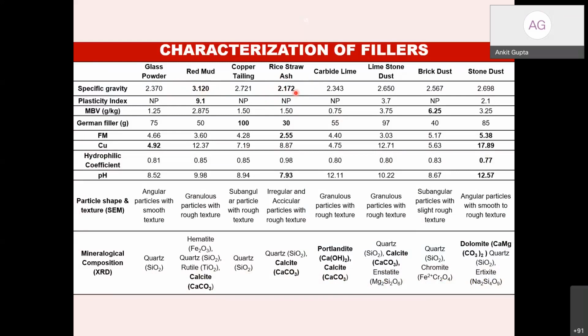Now the plasticity index I was telling, because as per the Ministry of Road Transport and Highways norms, anything having plasticity more than 4 cannot be used as a filler. But we found the red mud is having the PI value more than 4, but still it is giving very good results. So that's why we have our own logics. Rest all are non-plastic in nature or having values less than 4.